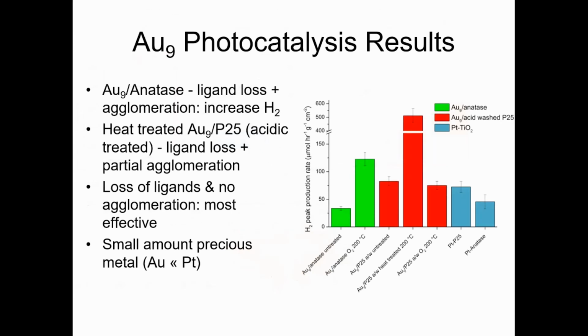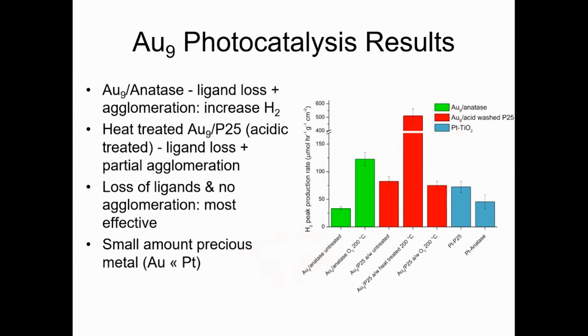Primarily, actual results show that we deposit the gold on different supports, as I said. They show the heat-treated Au9 on P25. It is even getting partial agglomeration, but it shows that when we have loss of the ligands and there is no aggregation degree, effective Au9 deposited on the titania shows a very nice result in the production of hydrogen.